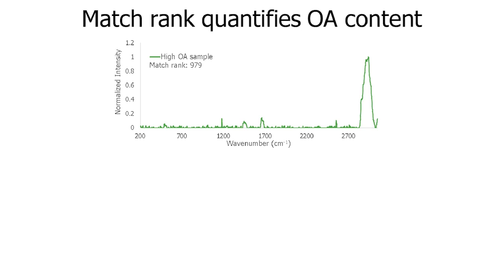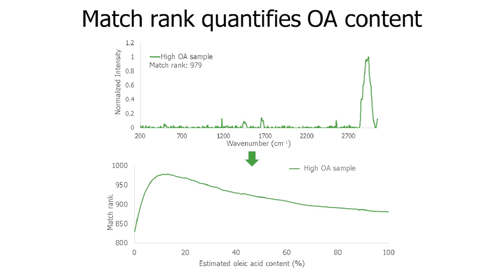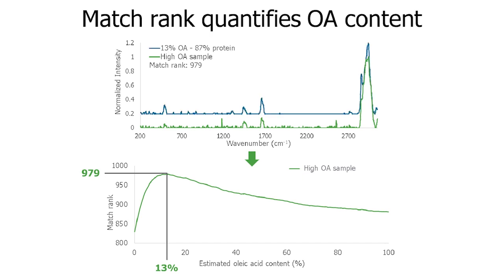So the highest match rank was used to quantify the relative percent of oleic acid versus protein per particle. In the example shown, the particle spectrum had the highest match rank against the 13% oleic acid and 87% protein composite, which indicated to us that this was going to be the highest match. So this particle was considered 13% oleic acid and 87% protein.